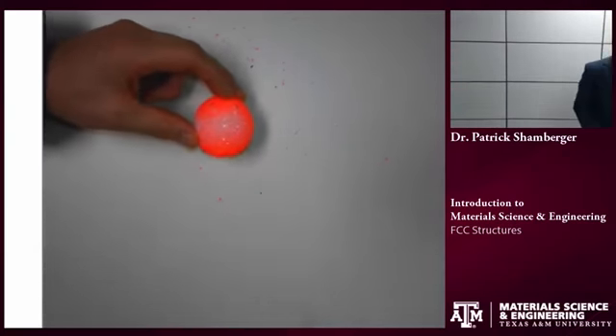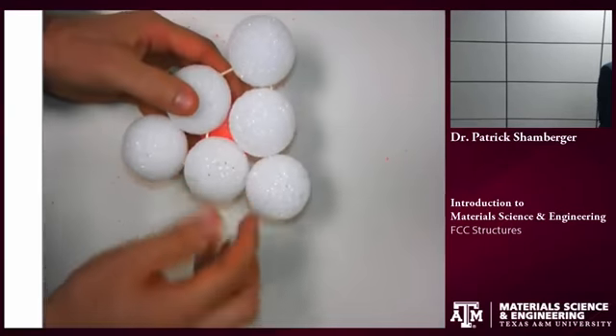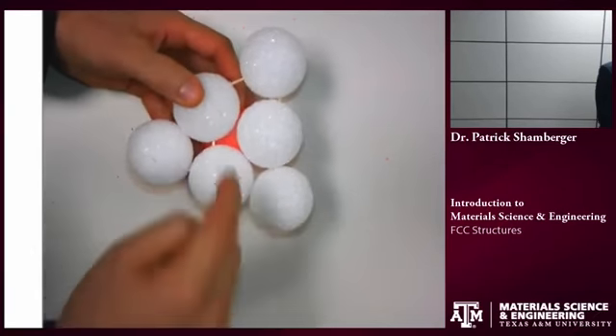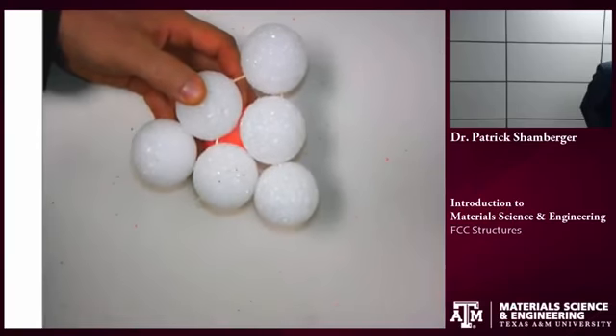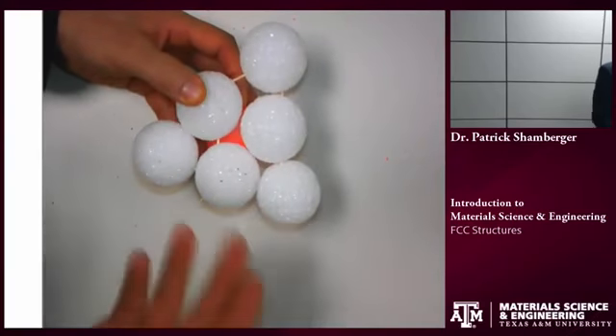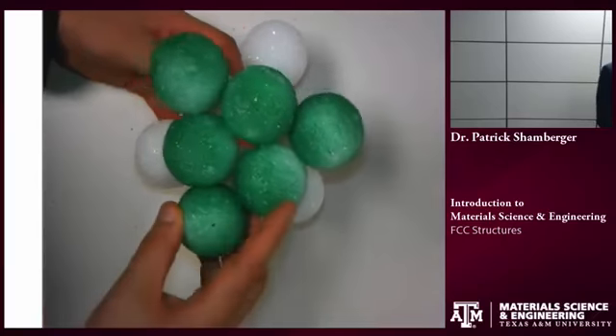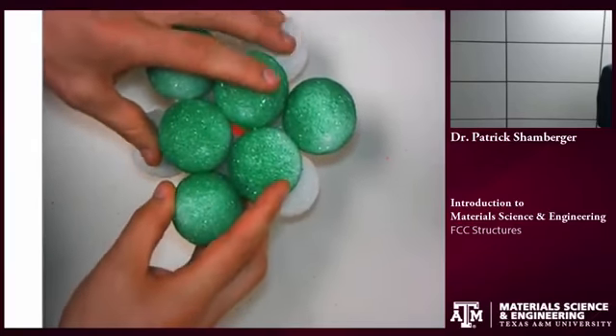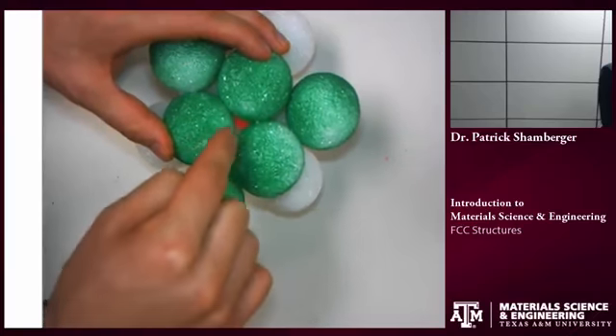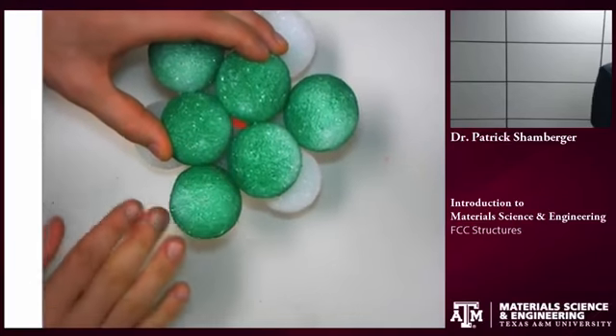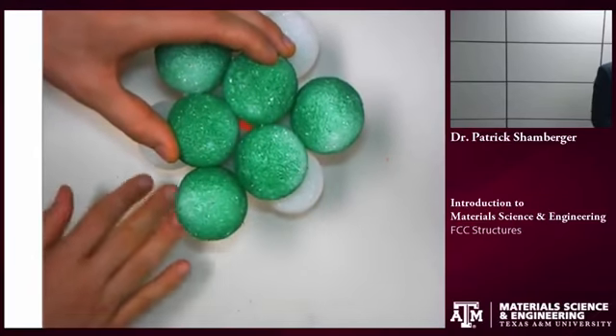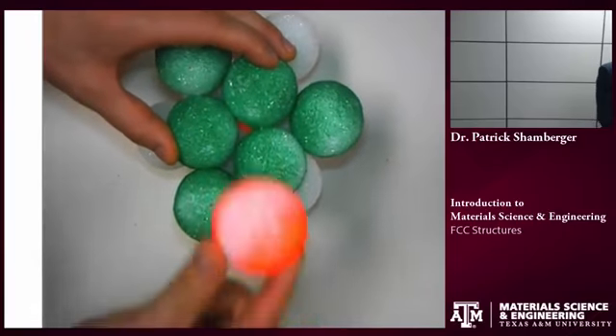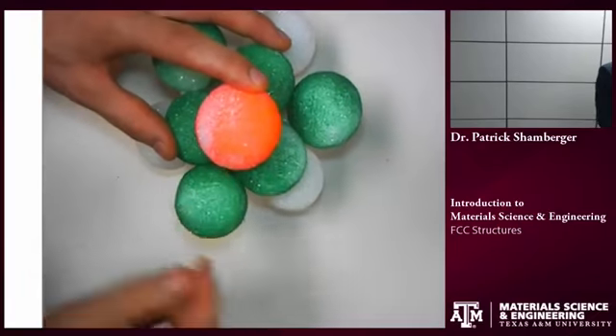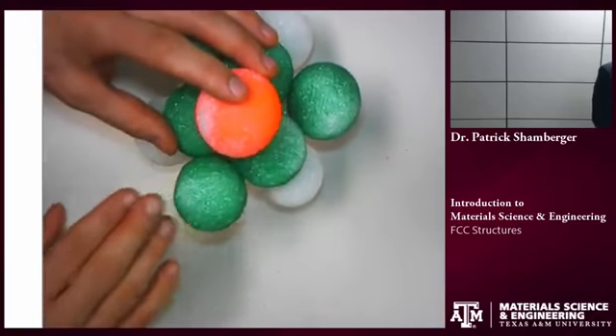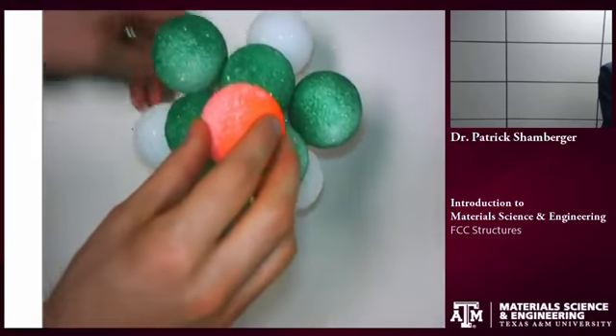So let's see what that looks like. We're going to start off with a single atom, and then put a close-packed plane on top of that. You can see that atom through the hole in this plane. So this is our A. B is offset a little bit. Now we're going to put another layer, C, which is also offset. And if you look closely, you can still see that orange atom through the hole of both layers. That means that neither B nor C is on top of the original A. Then finally, we place another layer on top of that very original layer. So A, B, C, A, and you can continue on.